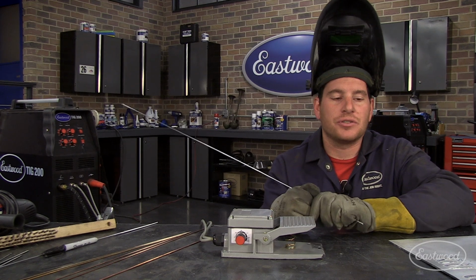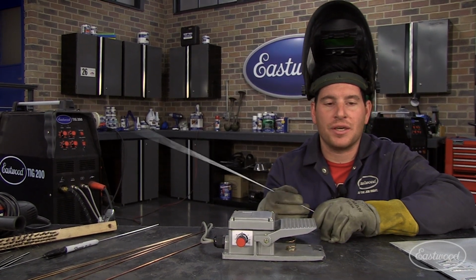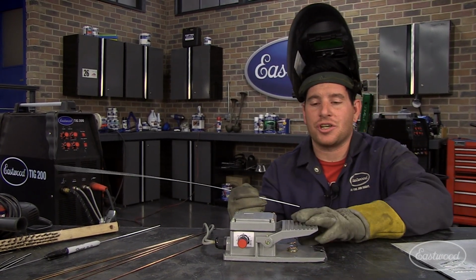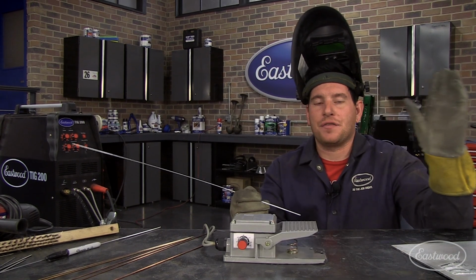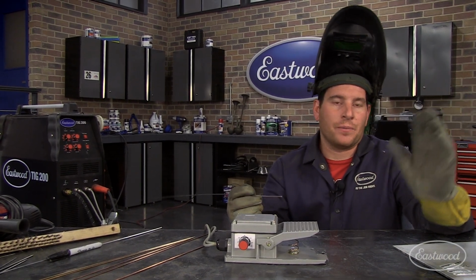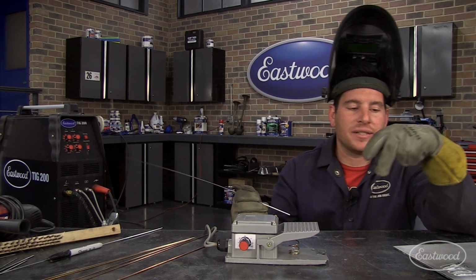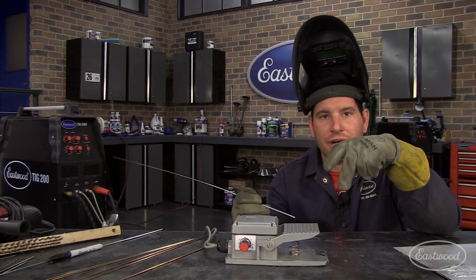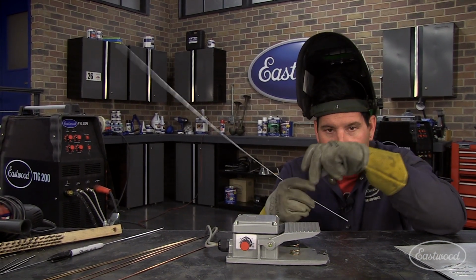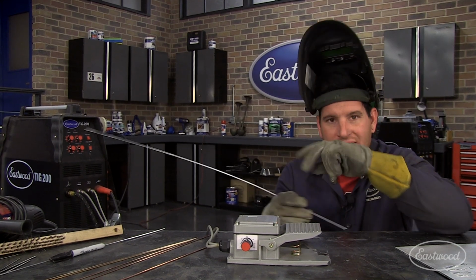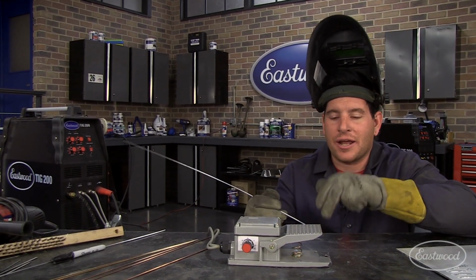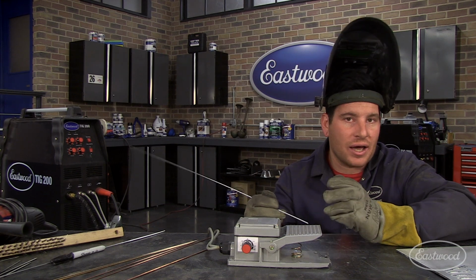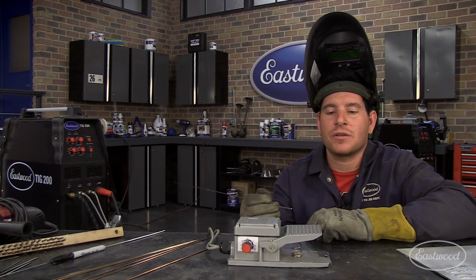Another thing you want to do when you're done welding an aluminum piece is you don't want to just be welding and let off the pedal. It's probably the worst thing you can do. What happens is if you look at the end of the weld, it's going to have a crater in it, or cracks. It'll have a crater with real small cracks in it. That's a void. That's an area that's going to fail over time. You don't want to do that.